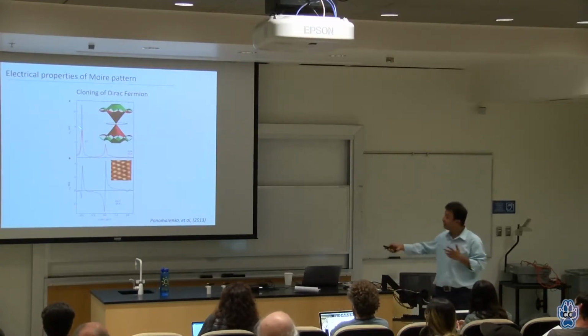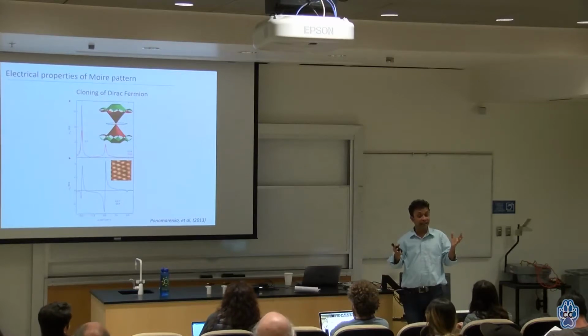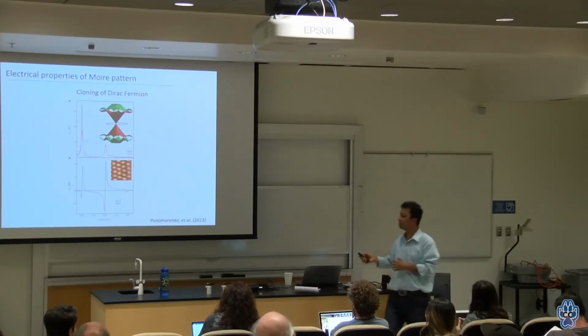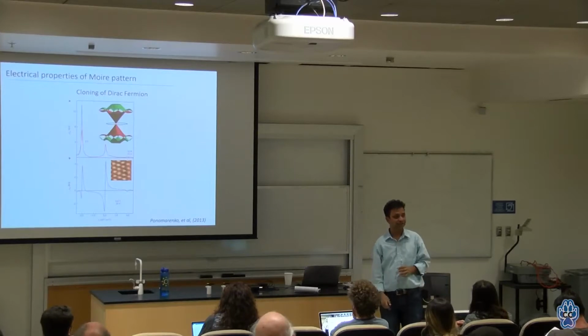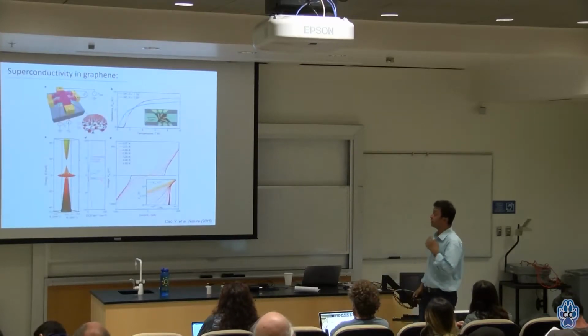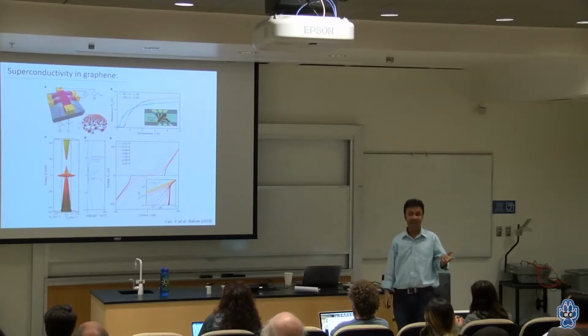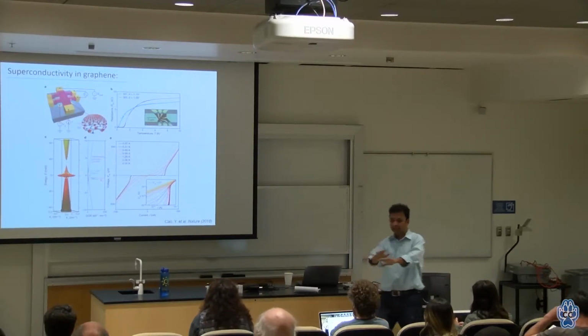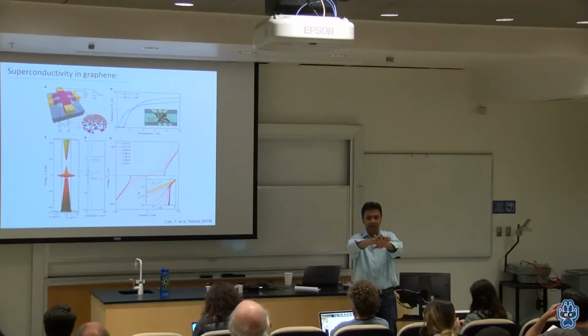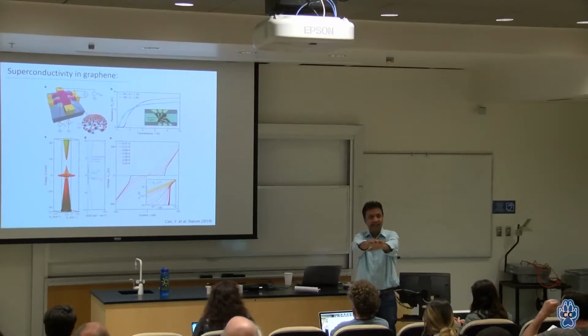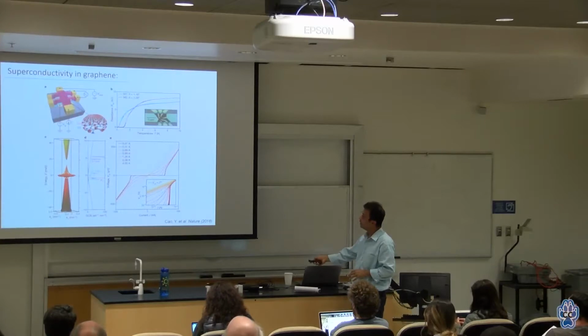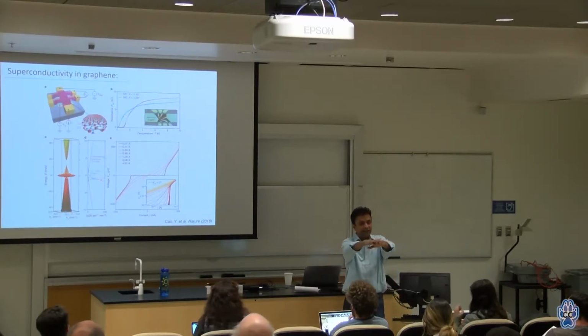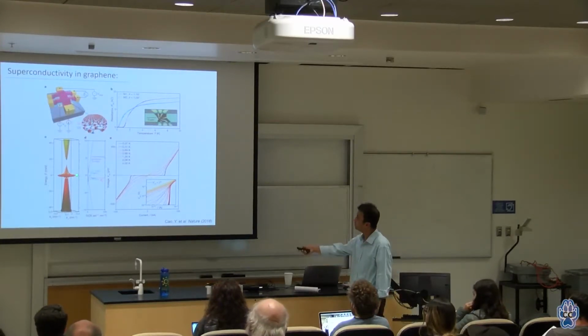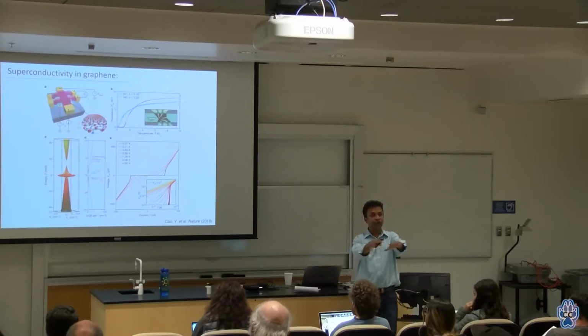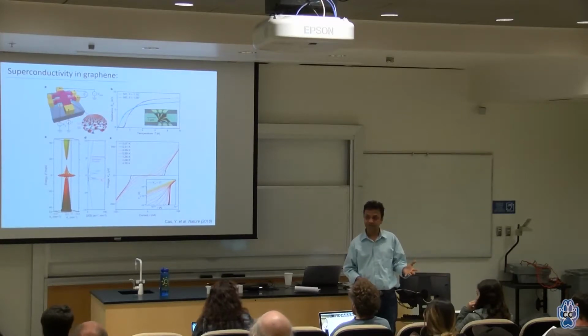So you can see that indeed you can change not only the band structures of the materials by the angular orientation of the system. A recent work, this just came out last month, found that at 1.1 degree, they call it the magic angle. When you have a magic angle, the band structures get flattened, like here, where you have a band structure flattened at zero. What happens is that you can obtain this new type of superconductivity.